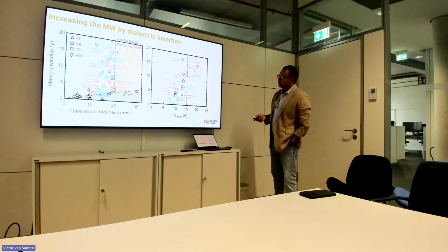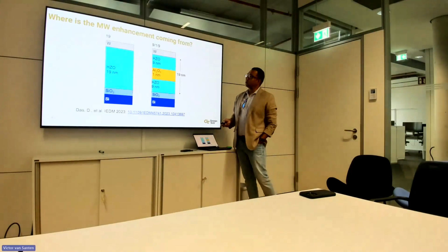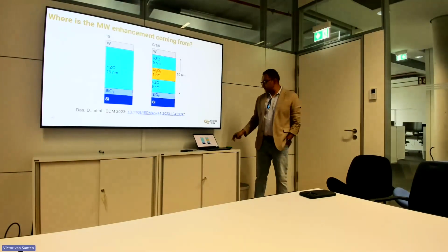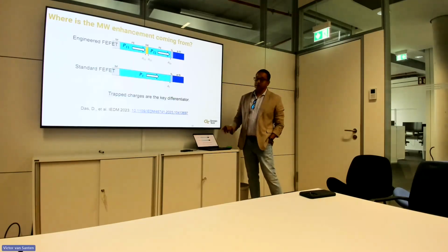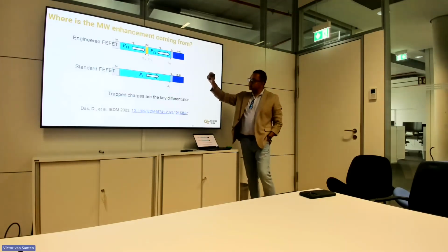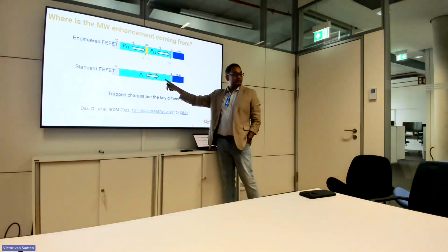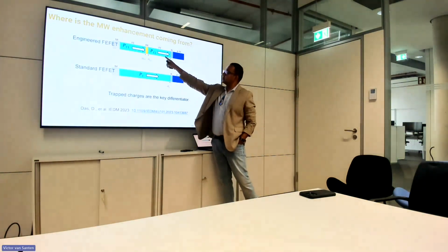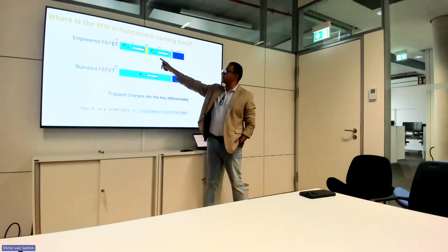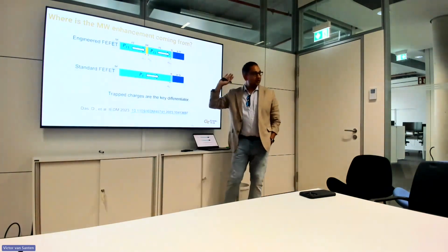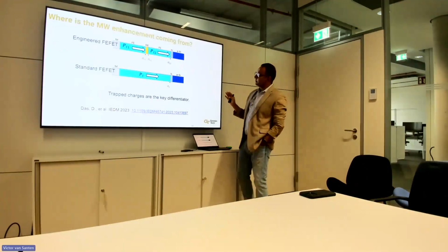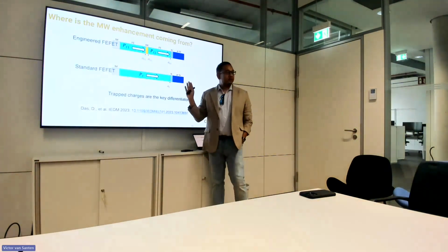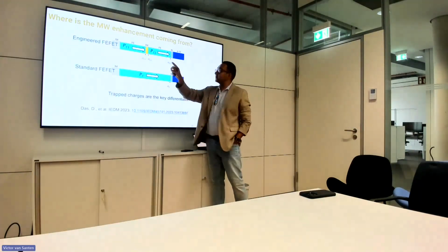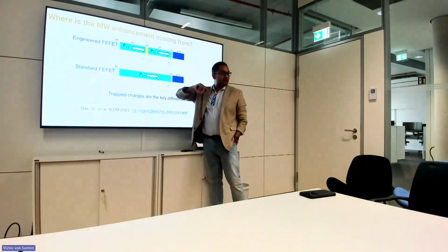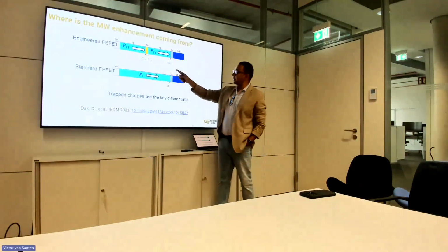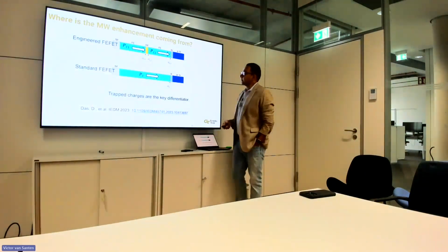Okay. So I'll quickly go over why we think this memory window enhancement is coming about. If I have a ferroelectric field effect transistor, this is a standard ferroelectric field effect transistor where we have just an HZO, but here what you have is HZO plus another dielectric material. Now, if you think about it, what is the main difference between these two structures? The main difference is the two additional interfaces that we get by putting in the dielectric layer in between. And whenever there is an interface, there are extra defects that we have here.